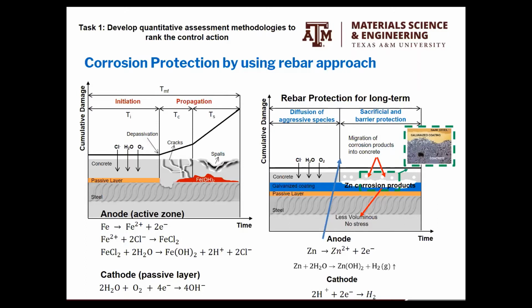Why? Because we have this same diagram where we have the initiation. As you see, we are assuming that the initiation of the same process as on the left is gonna last more time. Why? Because once the precursors of corrosion touch and migrate into the concrete and touch the zinc layer, what is gonna happen is we're gonna sacrifice it, the zinc is gonna react and start to dissolve, and also it's gonna form corrosion products.